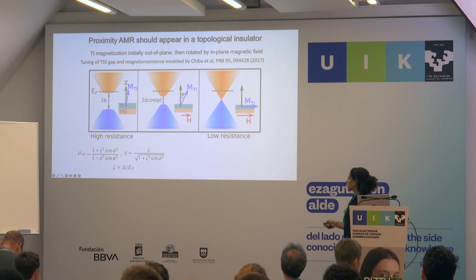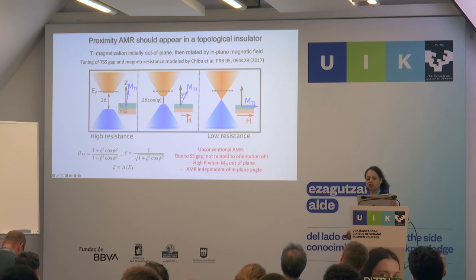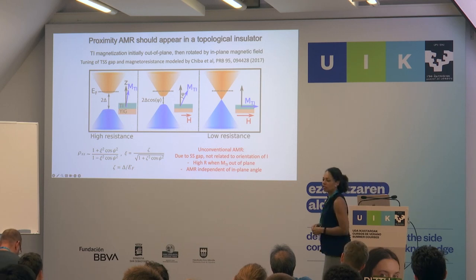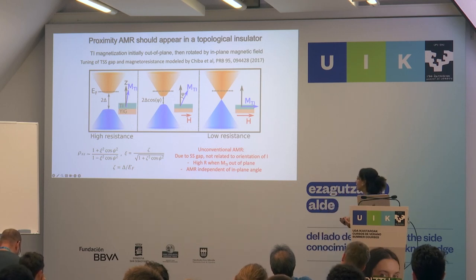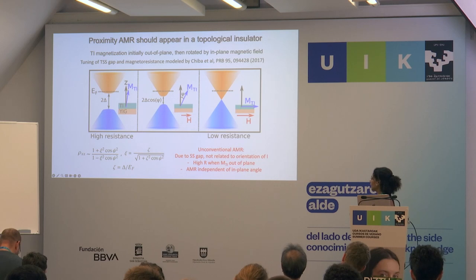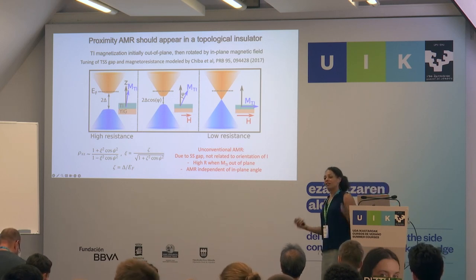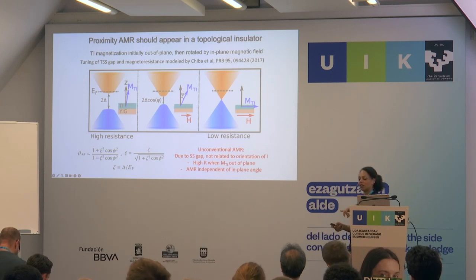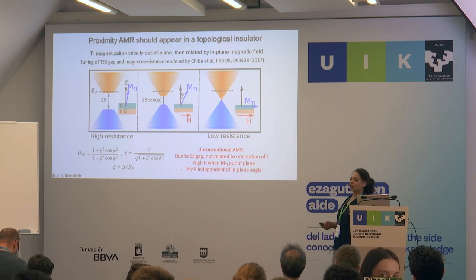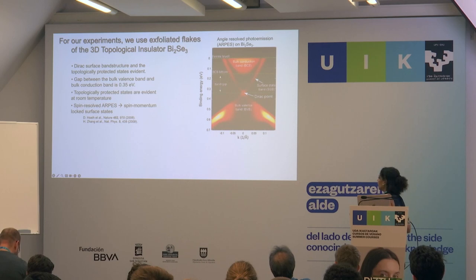There's a form that this sort of closing of the gap is expected to take. And I mentioned that this is really different from conventional anisotropic magnetoresistance, because in this case, it's due to a surface state gap and not related to the orientation of the current. And you expect a high resistance when the magnetization is out of plane, and it should be independent of in-plane angle. So that's completely opposite of standard AMR, which depends on the relative direction of the magnetic field and your current. So it only depends on your in-plane angle. Okay, so we set out to measure this.